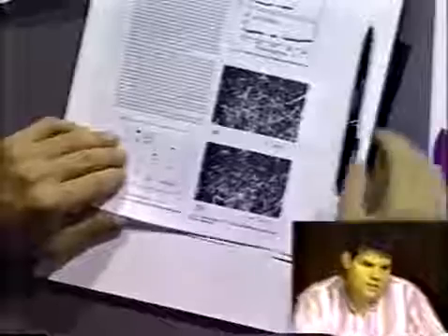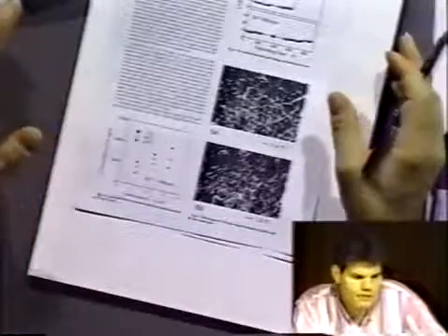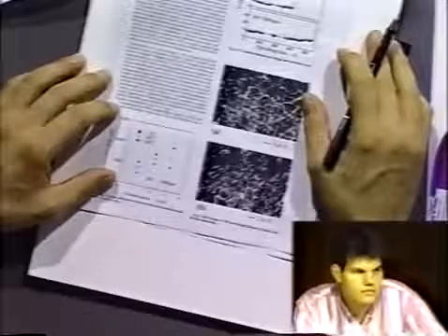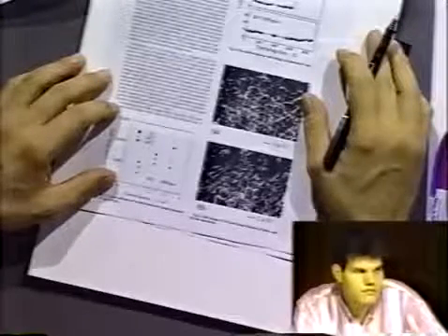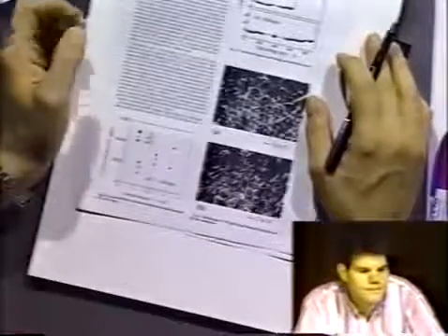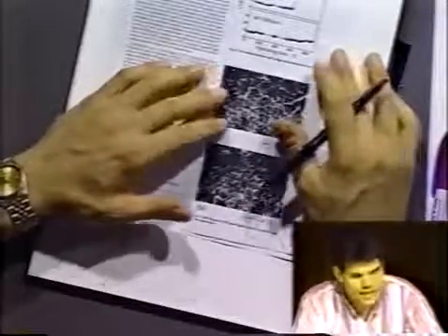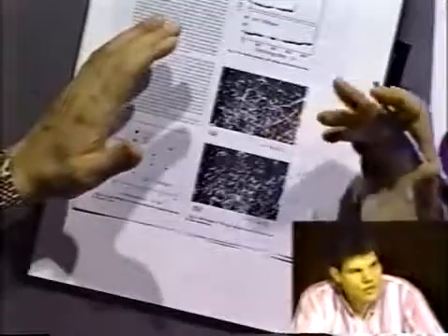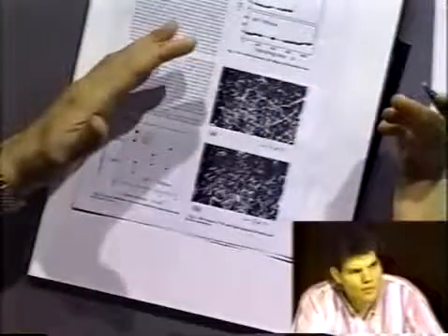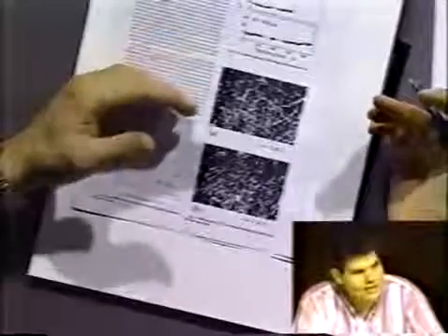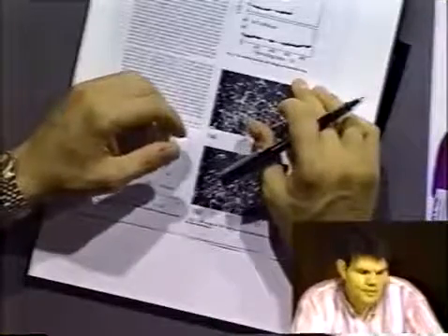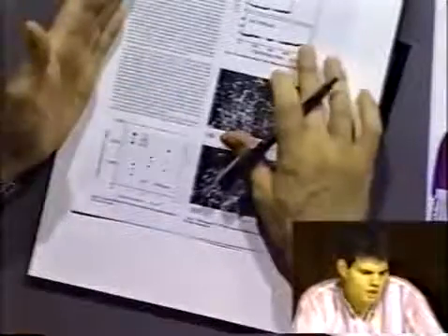But there is an ultimate limit. What do they say the limit is? What's happening at the end? What's happening to cause it to fail? We could grow a non-diamond layer at that level by increasing the concentration of the boron, which will... Yeah, they said if you try to make the doping more than 5,000 ppm in order to extend the life or reduce the overvoltage, it doesn't work. So you don't get a diamond-like film anymore, right? That would be mainly boron. Well, yeah, it just doesn't make a diamond-like film. But that's not even at 5,000 parts per million, it ends.